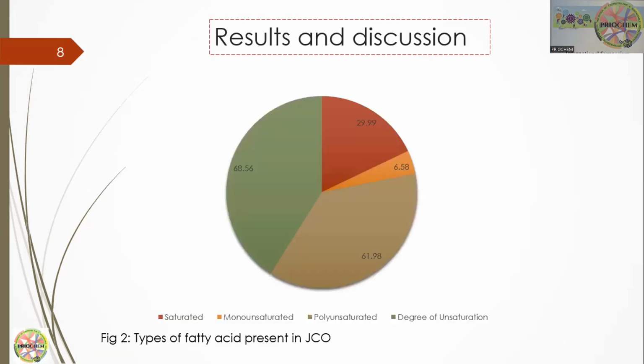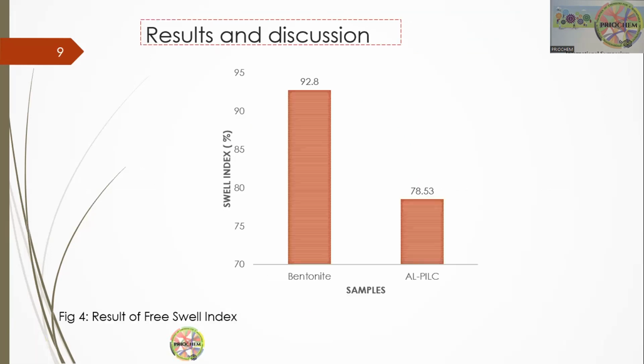This is how we divided it into saturated, monounsaturated, and polyunsaturated. So in all, the degree of unsaturation is around 68.56%. That means the oil is highly unsaturated, and it is going to affect the liquid product we are going to obtain. And then here is the crystallization of the bentonite and the aluminum pillared clay.